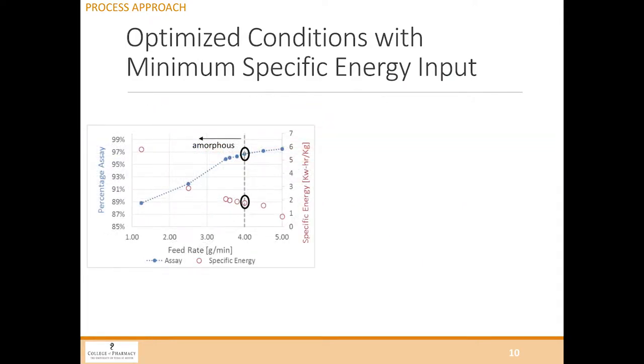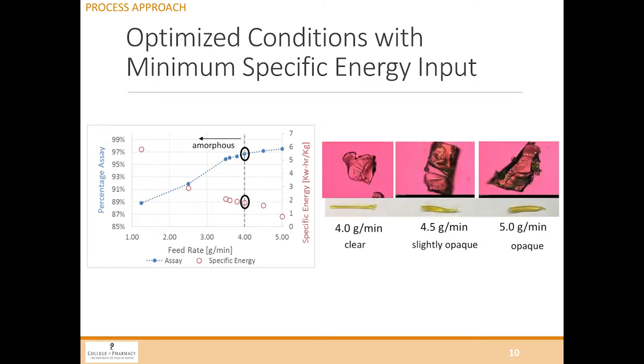Okay. And here's what we can do with the process, right? At certain screw speed, the higher the feed rate, we're actually reducing the energy. You can reduce to a certain level, all of a sudden it's not fully amorphous anymore. But then to make them fully amorphous, you're dealing with all the degradation. As you can see here, 4 grams per minute, it's clear. When you go to 5 grams per minute, actually it's opaque, it's not fully amorphous.